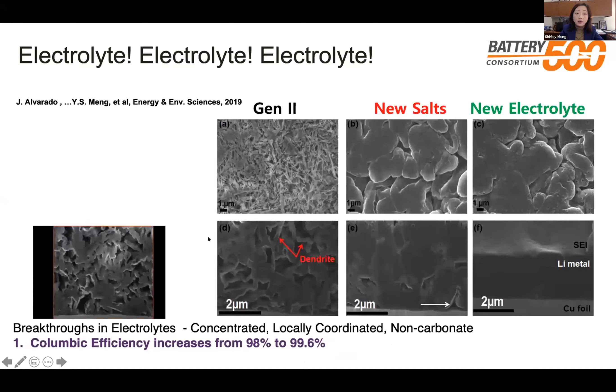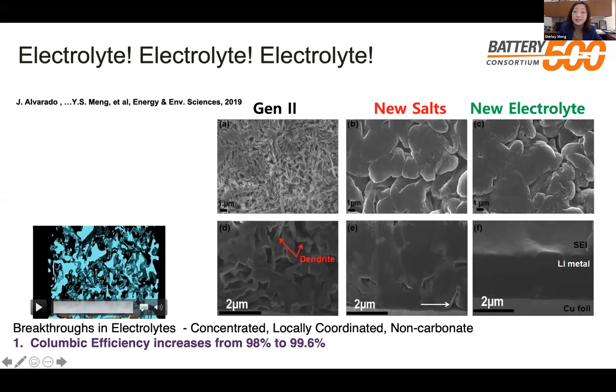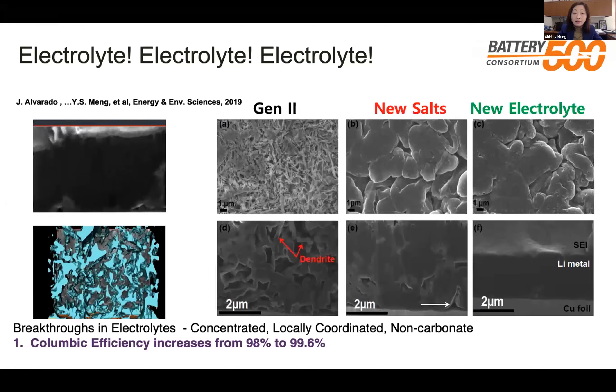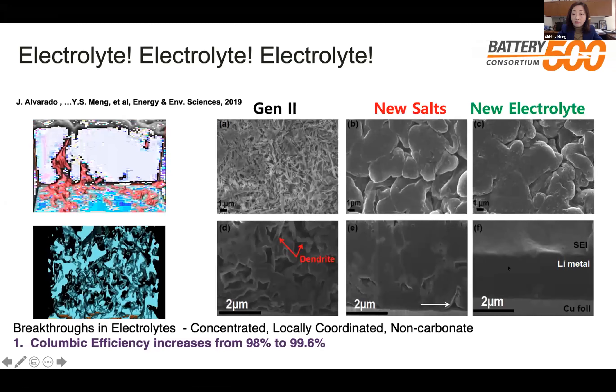In order to carefully study the morphology introduced by different electrolytes and salts for lithium metal, cryogenic cutting tools are very important. In generation-two electrolytes, electrochemically deposited lithium forms a highly tortuous, porous structure. They are still called lithium metal and still show BCC lithium by XRD, but the microstructure is completely different from the metals we have imagined. Moving to the new salts and electrolytes developed by Pacific Northwest National Laboratory — a key member of Battery 500 — we see completely different microstructures.